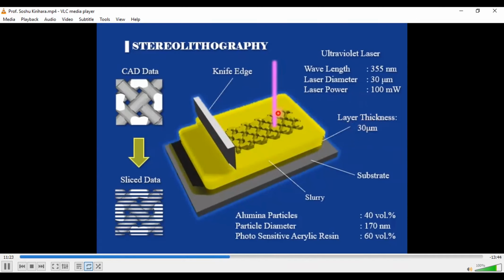The laser beam scans on the paste surface, so we can create solid two-dimensional structures. Through spreading, laser scanning, and layer by layer stacking, we can create three-dimensional structures in unsolidified paste materials. After the fabrication, the three-dimensional structures are taken out, washed and dried, and we can obtain the composite materials. This movie is the stereolithography fabrication.